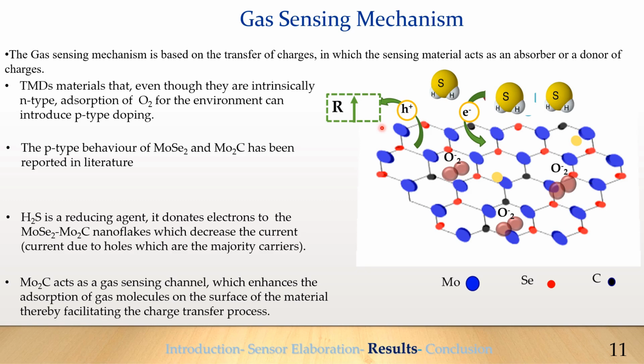The reason for the significant improvement in gas sensing performance of the hybrid material can be mainly attributed to the addition of Mo2C. It encourages the adsorption of gas molecules on the surface of the material, thereby facilitating the charge transfer process and enhancing the response of the gas sensor.